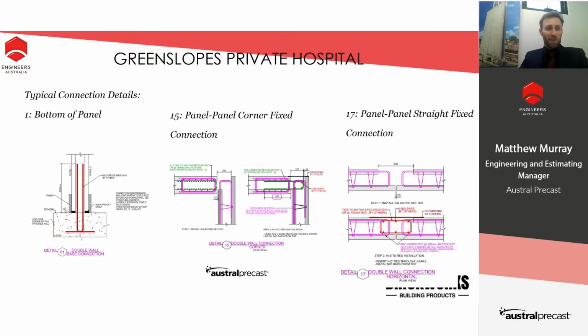So here's some of the specific details that we used for the hospital. Essentially here we have the starter bars with the 30mm packer for the bottom of panel connection. On the right hand side here, near the door opening, we would have a cage in one panel and a U-bar in the adjacent panel, whereby a hairpin was inserted into the panel on the left hand side before being pulled over on site and the vertical bars placed.